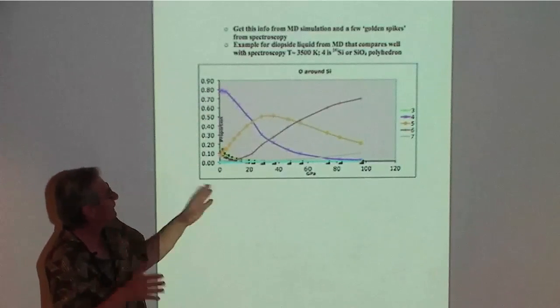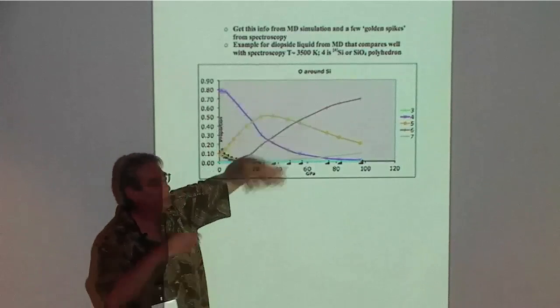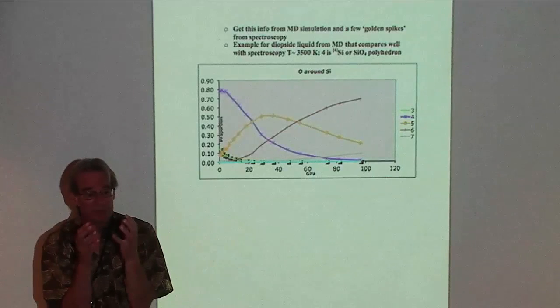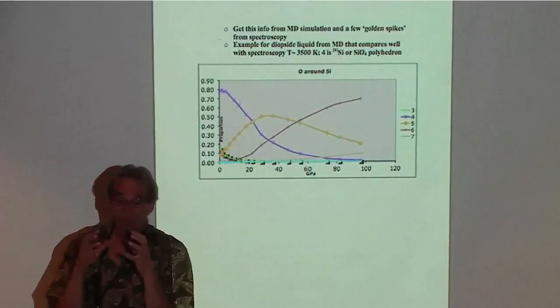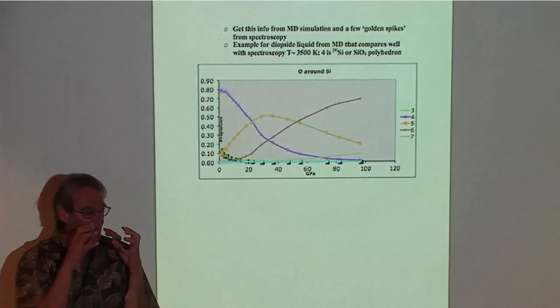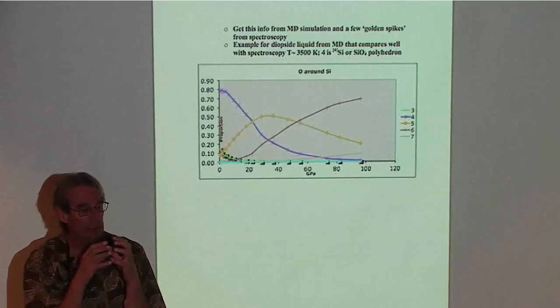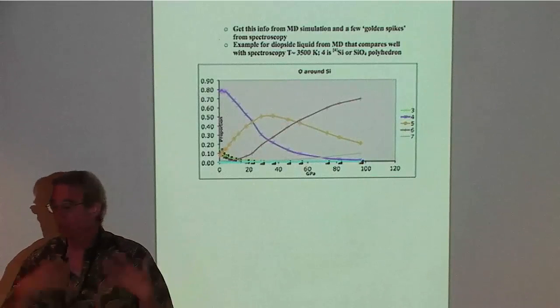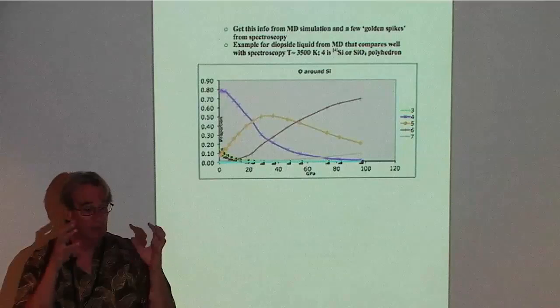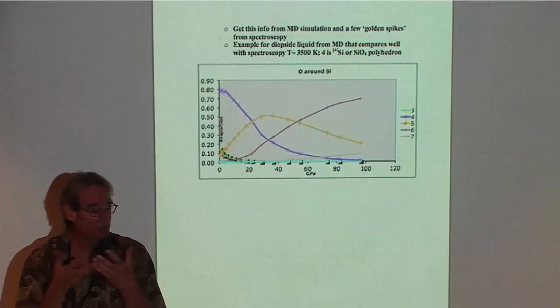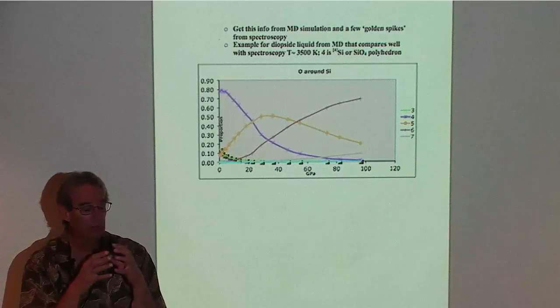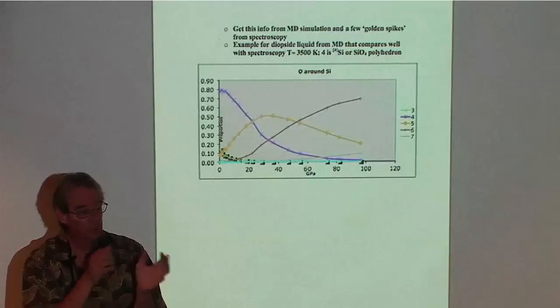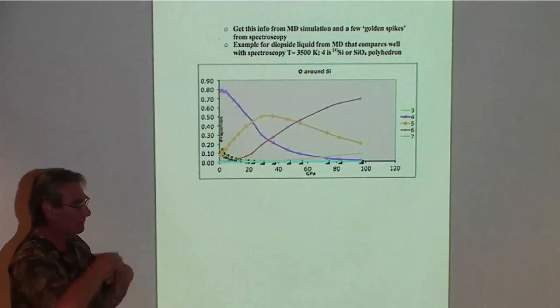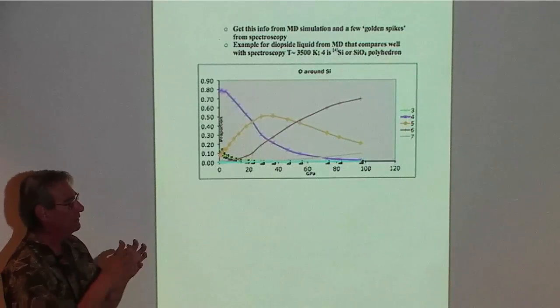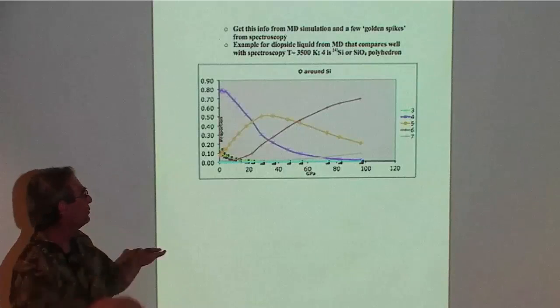But, and this is the point here, this is along an isotherm. You start squeezing this liquid. Unlike solids, which you can squeeze and elastically they deal with that squeezing, and then they undergo a phase transition. Like silica polymorphs, right? You start squeezing it, it densifies, but it's still alpha quartz or whatever. And then at some critical pressure, boom, it goes to coesite, right? And then finally it goes to stishovite, where the silica is in 6-fold coordination.